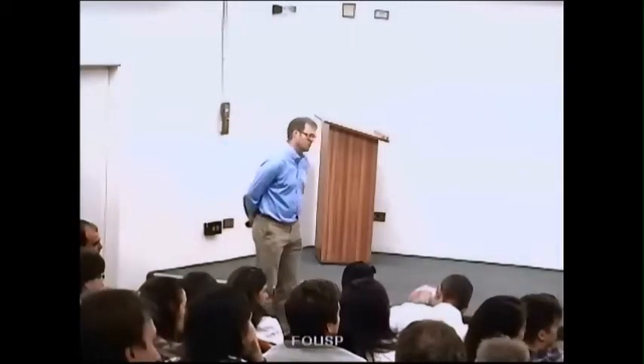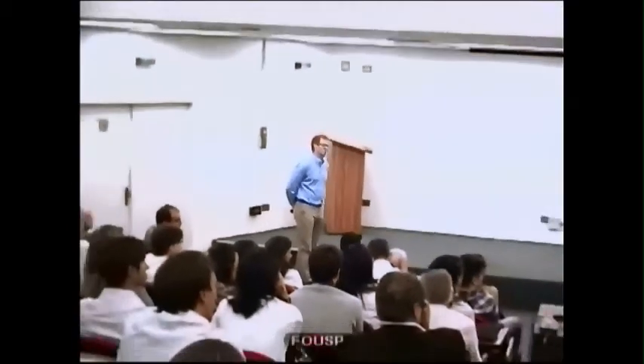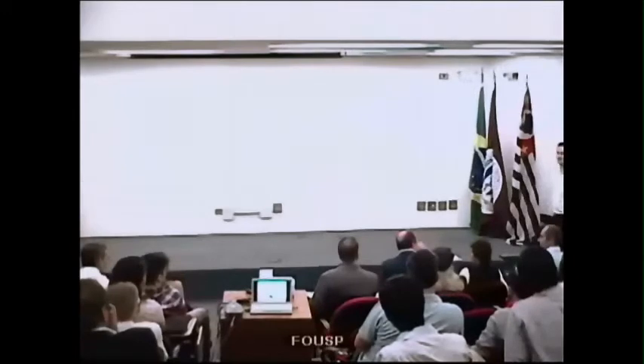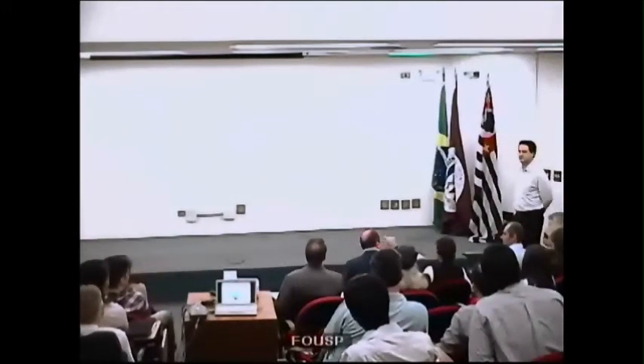Oh, good. Yeah, we were surprised, and that's a question that we thought was going to bother us in this denture tooth work. But when we took a look at the probability of failure versus number of cycles, if you assume that 1 year is 500,000, 1 million, or 1.5 million cycles, it doesn't shift it very much because there's such a strong curve or strong knee in that probability of failure versus cycles curve. So the question becomes less important than we thought it would be.